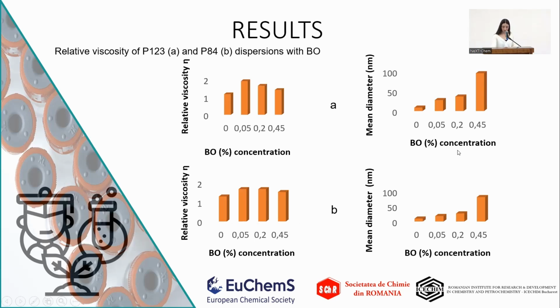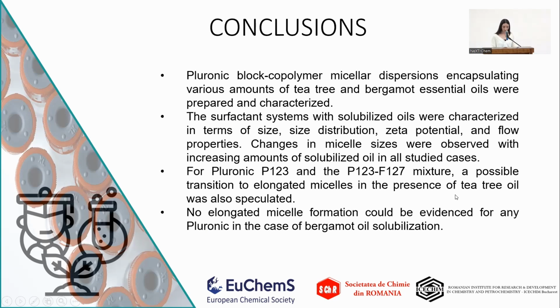And here as well. To conclude, pluronic block copolymers micellar dispersions encapsulating various amounts of tea tree and bergamot essential oils were prepared and characterized. The surfactant systems with solubilized oils were characterized in terms of size distribution, zeta potential, and flow properties.